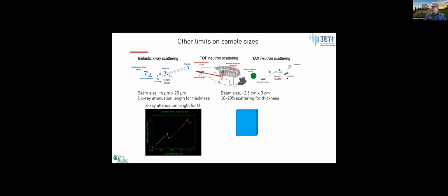To get a little more detailed, when we're talking about actinides in particular, they have very short X-ray attenuation lengths, of course, because of their high density, which means that you're not going to scatter from a lot of material to begin with. So it's well matched to using X-rays on small samples. Your attenuation length, for example, with uranium shown here, is on the order of 10 microns for the energies that you're going to be looking at on HERIX, compared to centimeter scale for the neutron experiments. So you can use very small samples, and if you have a focused beam, it works even better, and so it's well matched.